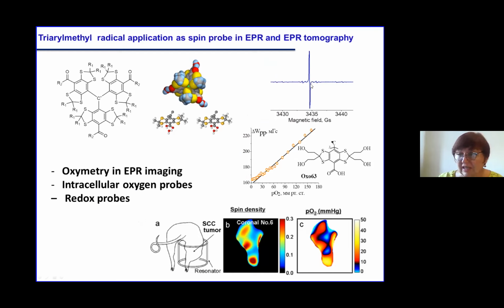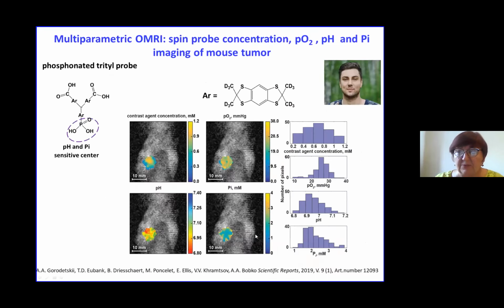measuring the EPR line width at different concentrations of oxygen. And knowing this dependence, one can measure EPR tomography and reconstruct the concentration of oxygen in different parts of the sample of small animals. And as a result, for example, this work, I'm not the author of this work. This work was done by Artem Gorodetsky in cooperation with Valery Khramtsov.